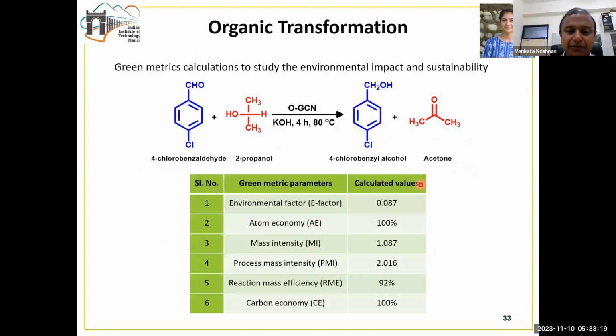Then we have analyzed the different green metrics parameters. These include the environmental factor, atom economy, mass intensity, process mass intensity, reaction mass efficiency, and the carbon economy. We got quite good values for these parameters, which indicates that our reactions are green in nature. Because anything which we call green, we must ask how green, how much green. So it all has to be quantified using some numeric parameters, and these green metrics parameters are the ones which can quantify the greenness of this work. So we have done a detailed calculation.